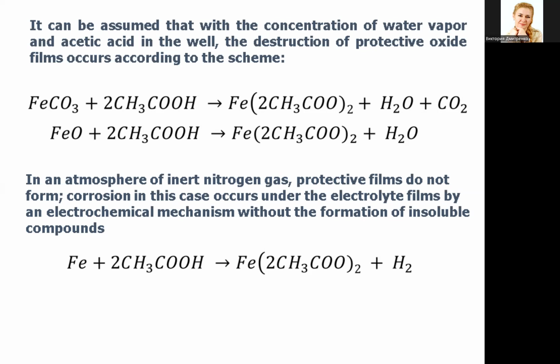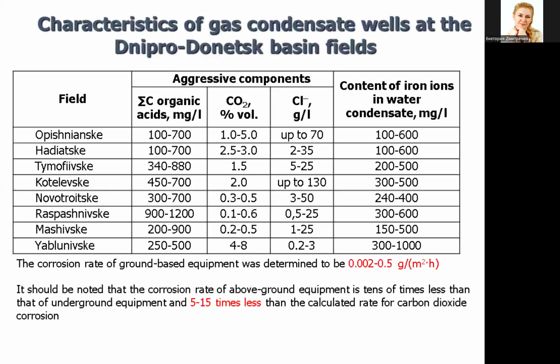The highest corrosion rate is at the beginning of droplet water condensation, since the main factors influencing the corrosion rate, acid concentration and temperature, are greatest at this point. The presence of carboxylic acid in condensation water shifts the interval for the beginning of aqueous fluid condensation in the well towards higher temperatures and depth compared to pure carbon dioxide corrosion. The intensity of corrosion of the well bore was determined by gravimetric methods on a sample installed in the tubing and visually on the tubing raised during repair. At these deposits, there is a correlation between the concentration of ions and the concentration of organic acids in the condensation water.